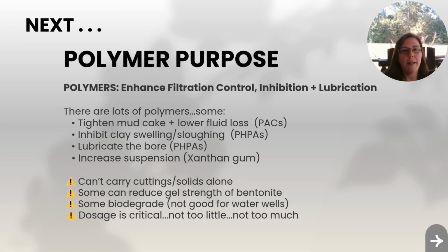Now, here's why. Because hey, I'm just gonna add a little bit of a polymer, like a little bit of a PHPA, because I wanna save money, and I don't need much anyway, and I don't wanna build a lot of viscosity. Certain chemistries, like PHPA, if you don't add the right amount to your fluid, it will actually act totally different than a clay and shale inhibitor. It'll start acting like a flocculant. And what that means is it will basically crush your whole mud system.